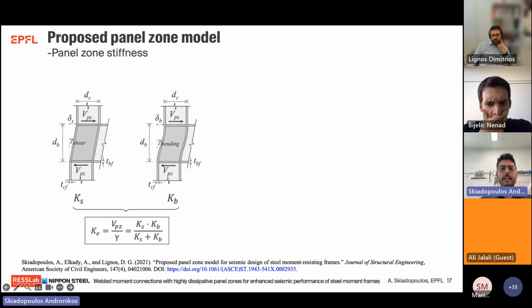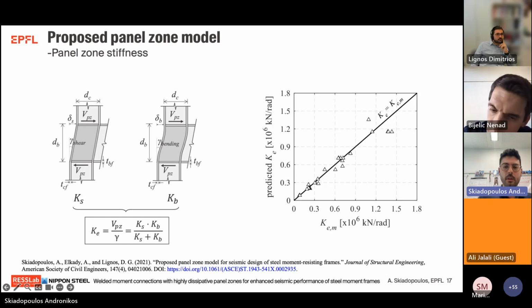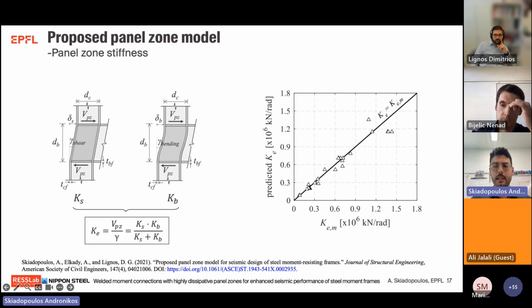So first, we proposed an elastic stiffness that accounts for both the bending as well as the shear deformation mode within the panel zone. These deformation modes are assumed to be working in series, as shown by the given equation of Ke. Note here that this is especially critical for panel zones with aspect ratios higher than 1.5, where the bending deformation mode may be critical. By comparing the proposed panel zone stiffness with the measured one from the experimental data that we collected, we see that the proposed model captures the elastic stiffness very accurately.